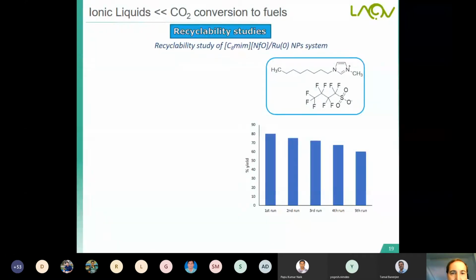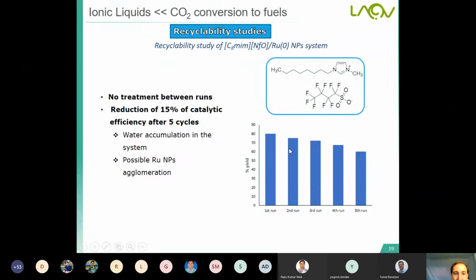Then we prove that it's possible to recycle, and this is an important point in catalysis, an important point to use ionic liquids, and we prove the recyclability of this ionic liquid and ruthenium zero nanoparticle system. After 5 cycles, we observe a reduction of 15% of the catalytic efficiency without treatment between runs. And the reason for this reduction is the water accumulation in the system and also the possible ruthenium nanoparticle agglomeration.